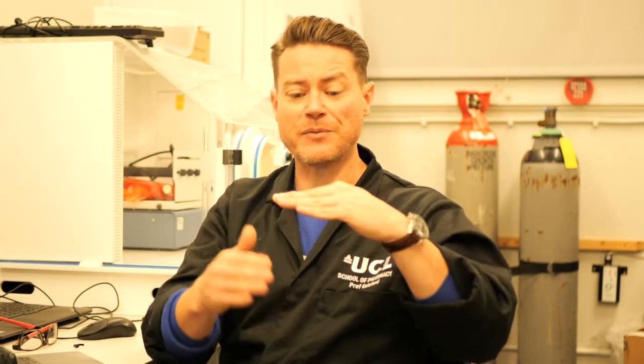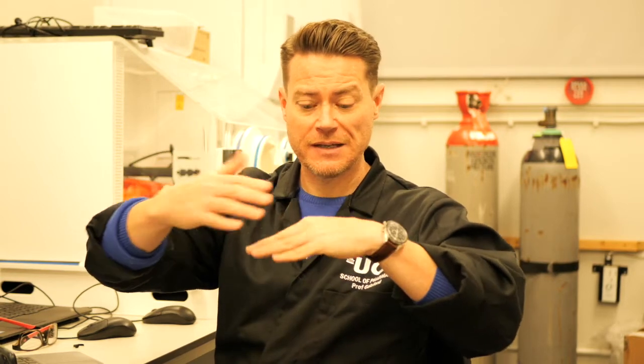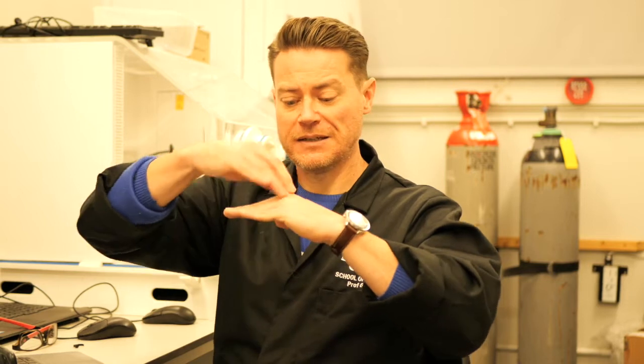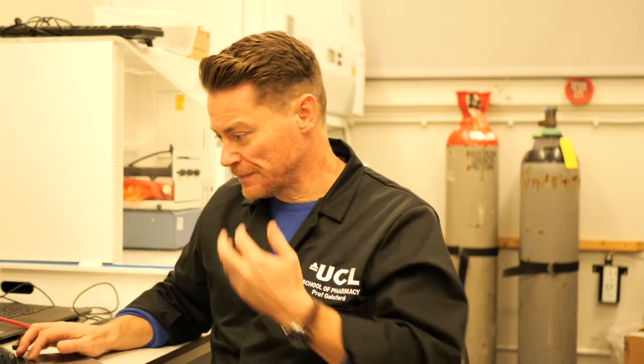So by measuring how the tip responds as it's bounced across the surface, you can tell something about the mechanical strength of your sample. And then to image your sample, you simply bounce the tip at one point and measure how the signal is decaying. Then you move the tip to another point and do the measurement again. So you're still building up a topographical image, but now it's point-based as you move across the surface of your sample.